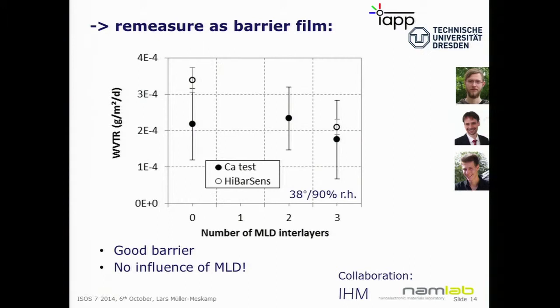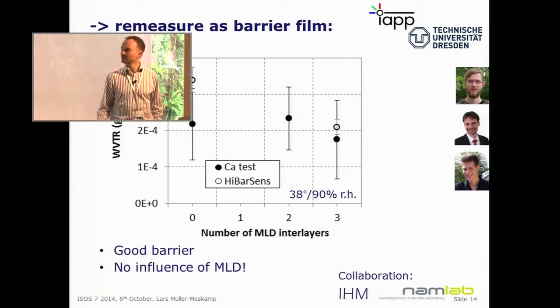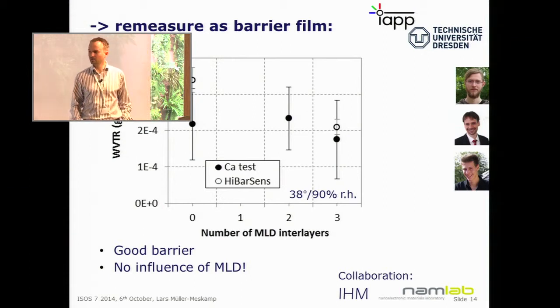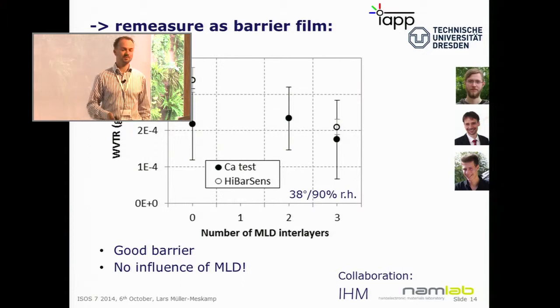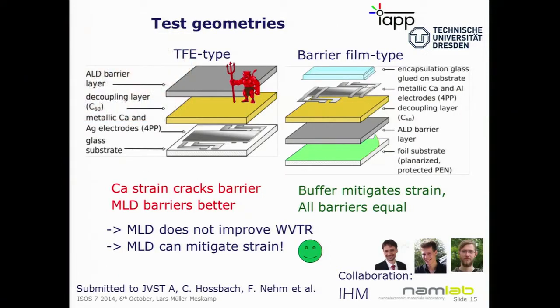These open dots are a different method, a laser spectroscopy-based permeation measurement, and they confirm it's basically the same type of barrier. Okay, it's a good barrier, but no influence of the MLD. So what's happening is probably that if you have the TFE type of encapsulation, so you have the calcium test down here, and you have the decoupling layer and the ALD layer, then the calcium breaks the barrier, even if there's a decoupling layer. Probably it's a delamination at the bottom part. And in this case, the MLD barriers perform much better, because probably they are able to mitigate the strain somehow.